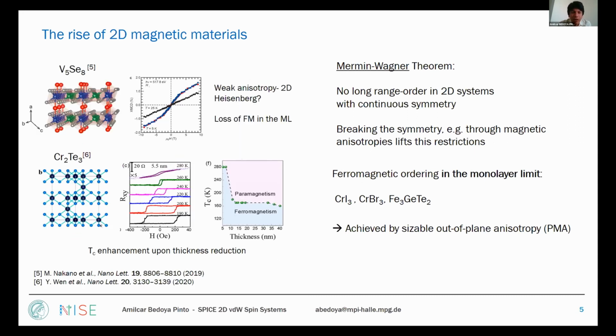We will hear maybe later today the example of vanadium selenide, because this is also an interesting example of a film that loses magnetism in the monolayer regime, similar to what happens in chromium germanium telluride. When you go from the bilayer to the monolayer, you don't have a magnetic order anymore, presumably because of this weak anisotropy and the Heisenberg character of the system.